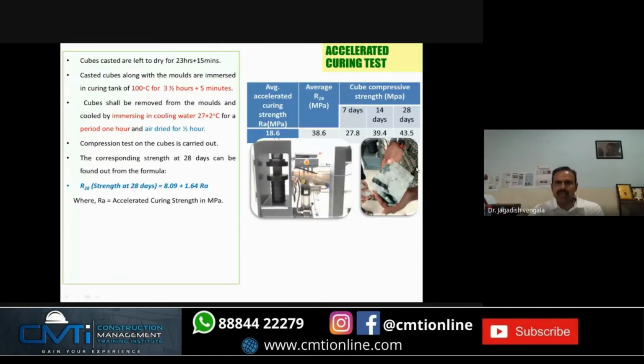And then we did the accelerated curing test because we cannot wait, particularly since BTech projects are 3 months, 4 months. When you start the work, you just have to find out the next day. How do you measure the strength, the projected 28 day strength, using accelerated curing test? You know the procedure, right?